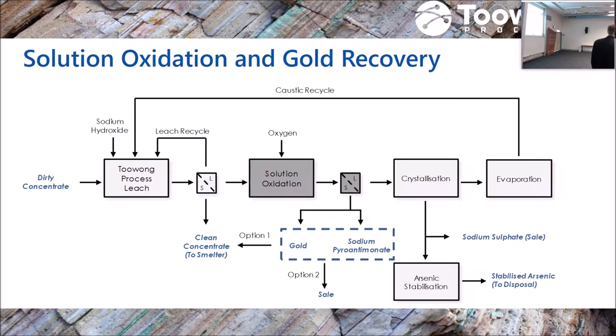We basically oxidise everything, all the sulfur species, to sulfate. So then we've got it in a stable form, sulfate, and we can deal with that sulfate. A little bit of gold sometimes leaches in here, but because we run a very low sulfide regime, we don't get a lot of gold solubilisation. If gold does solubilise, it'll pop out here. As soon as you break down the sulfides, whether it's S2- or HS-, or some of the higher sulfates, that gold will drop out.